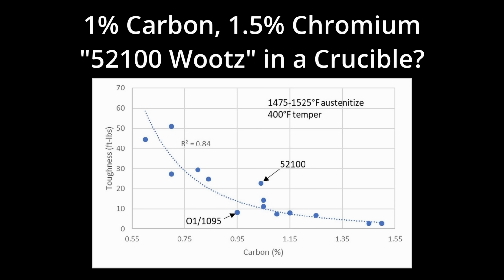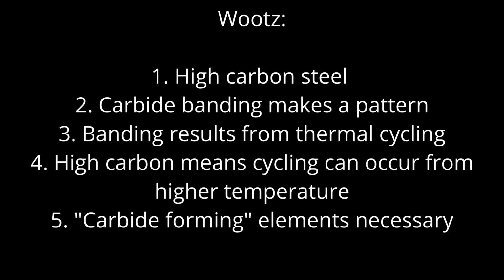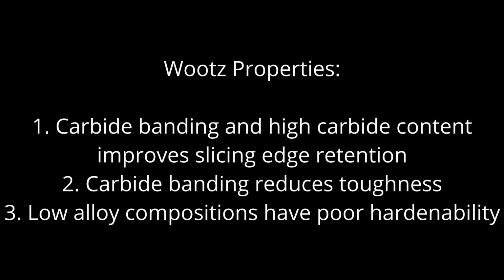So to summarize, Wootz Damascus, it's a high carbon steel with carbide banding in it. That carbide banding creates a macroscopic pattern, especially when etched. So we get the banding through a combination of high carbon content so that we can thermocycle without overheating and dissolving all of the carbide. And usually a little bit of a carbide former is necessary, such as vanadium, niobium, chromium, or manganese. In this case, we studied one with a small content of niobium. The banding of the carbides does help with edge retention, but it's also bad for toughness, so there's a trade-off. The low hardenability of simple Wootz compositions makes it difficult to achieve full hardness without a water quench. I could not get full hardness without a water quench.